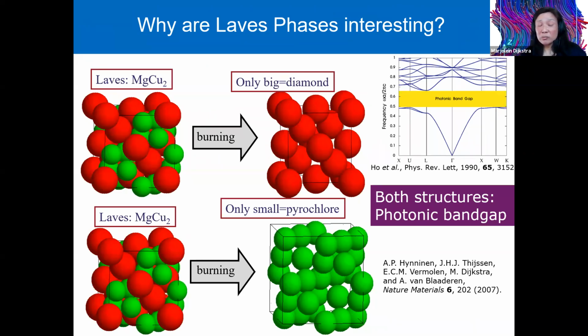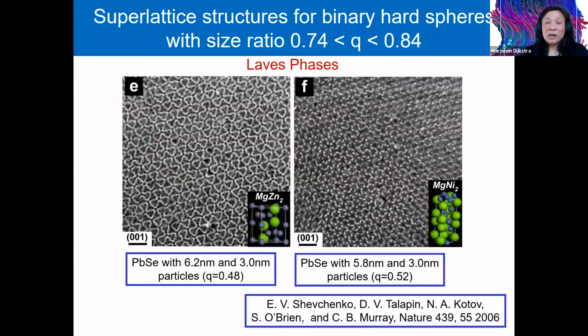And so if you can self-assemble, using colloidal hard spheres, this Laves phase, the magnesium copper 2 phase, one can burn away, for instance, one of these sublattices, and one ends up with a diamond structure or with the pyrochlore structure, and both the diamond and the pyrochlore structure exhibit a photonic band gap in the visible, as can be shown in this band diagram. And so this would be a very interesting way to produce a photonic band gap structure. However, these Laves phases so far have only been seen in nanoparticle suspensions and never for the bigger colloidal suspensions, which are relevant if you want to make a photonic band gap structure.